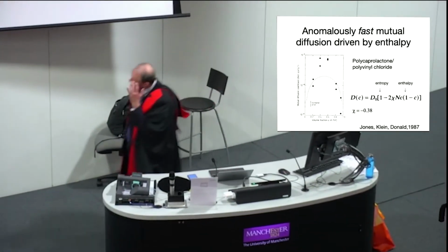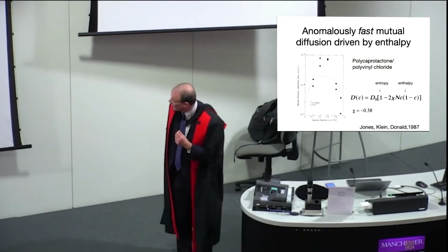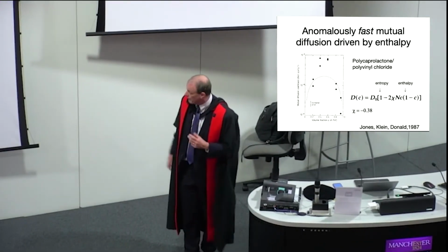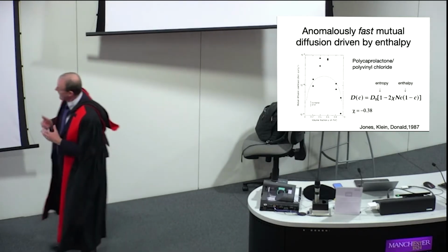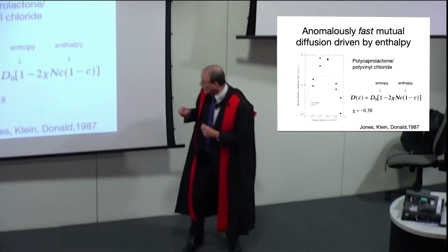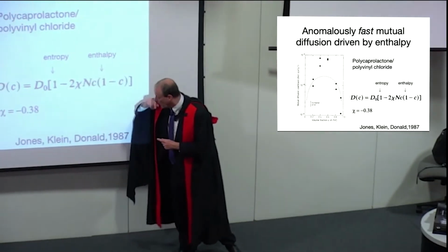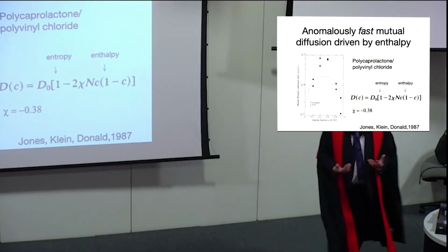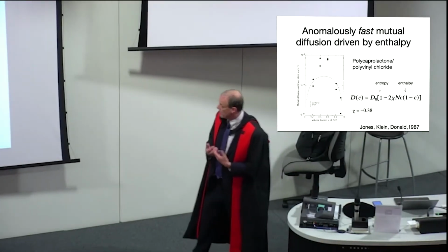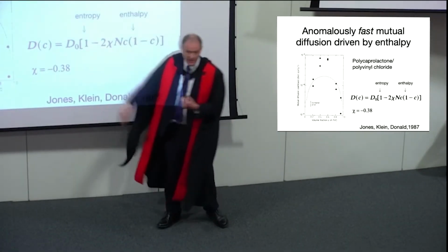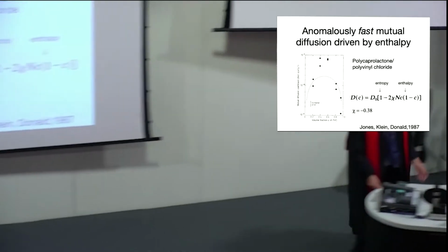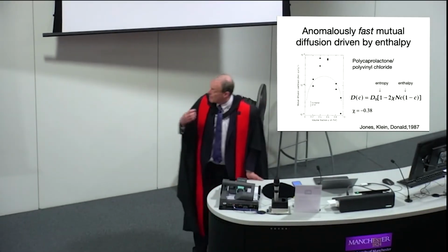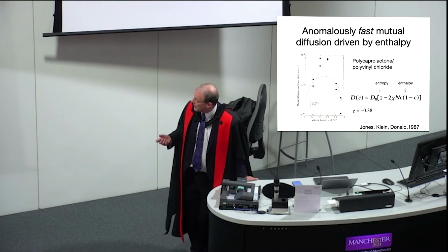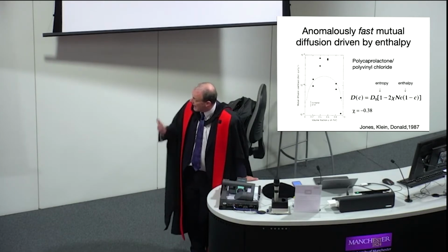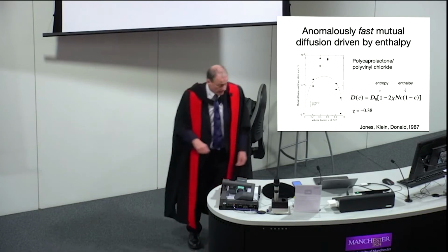I just mentioned the anomalously fast one because this is what I did my PhD on, so it's interesting in that way. And really it just follows, because if you write down the second derivative of free energy, you get this term here which has got an n in. So chi is a number which is of order 1, and it's negative if the two things want to mix. So the factor n in there can make this term much bigger than this term, which is essentially the entropy. So actually in miscible polymer blends, diffusion can be much faster than you'd expect in the normal run of things, and it also has a very strong concentration dependence.